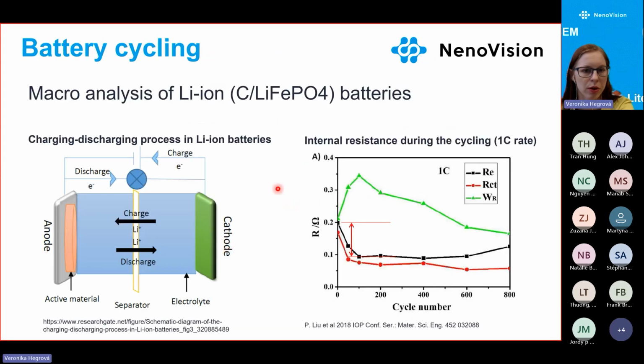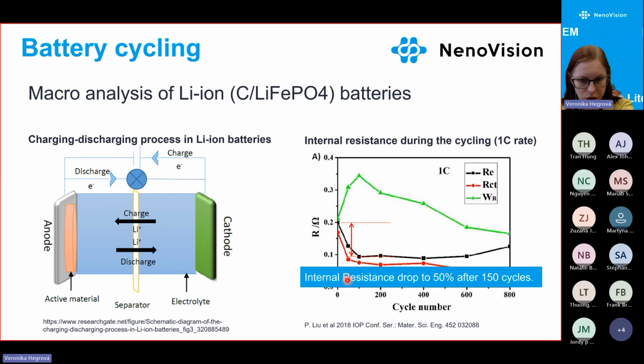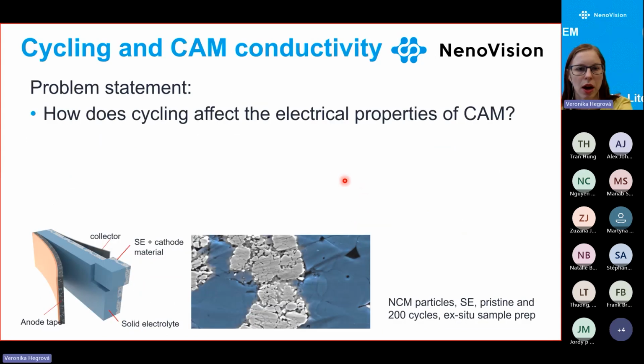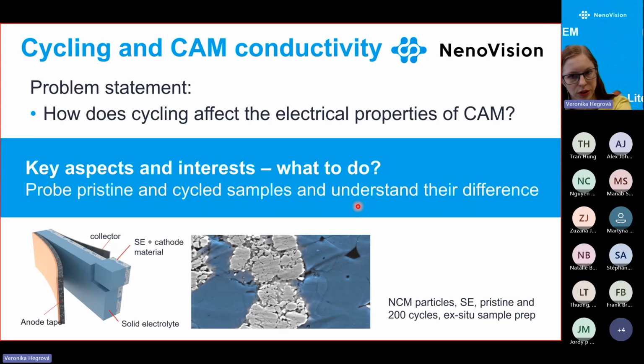From the macroscopical analysis of lithium ions, these discharging processes make a drop in the internal resistance to 50% in 150 cycles. So it's quite a small number, I would say, regarding the cycles, and it should be analyzed and understood in order to make the performance better and make the number of cycles larger. And so the question is, how does the cycling affect the electrical properties of cathode active material in the microscale? So we need to probe the pristine and cycled sample and compare the data.